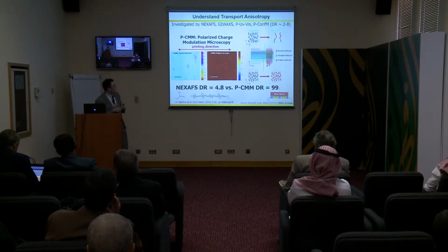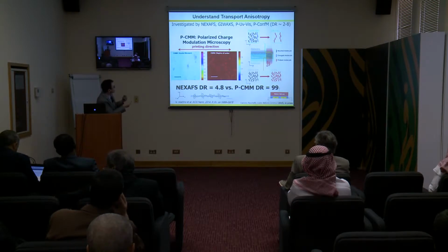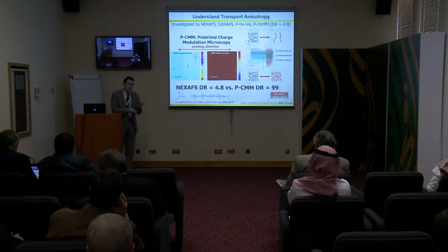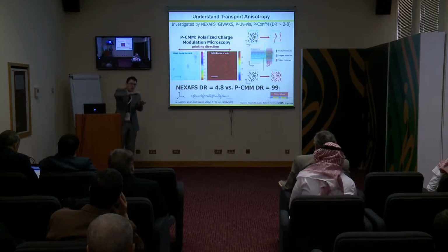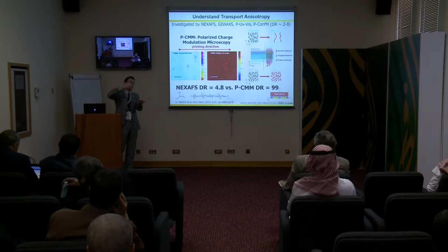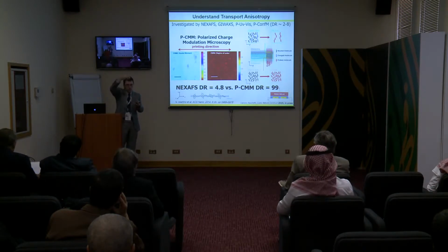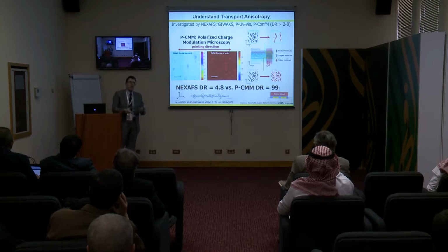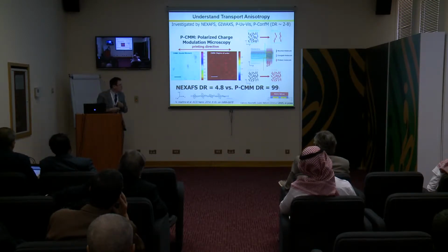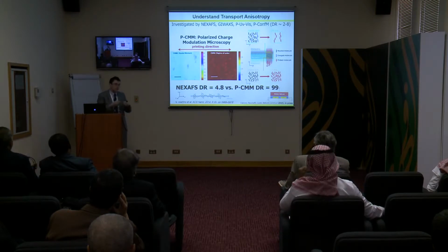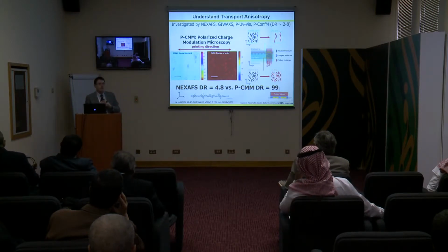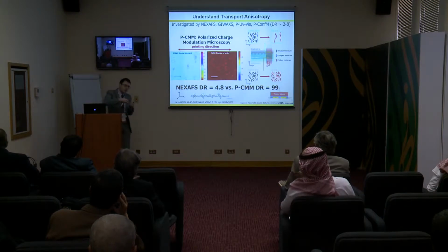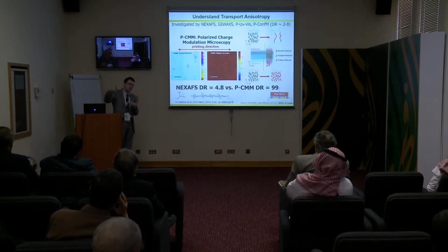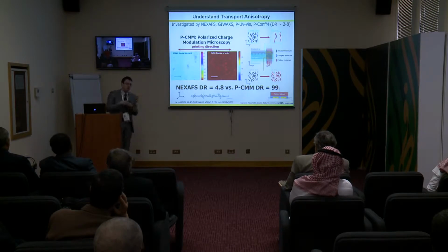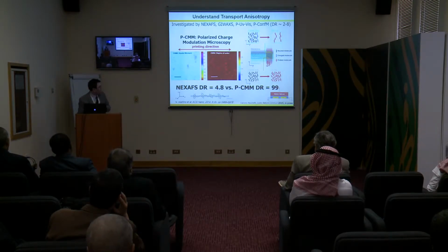And this is really because these macromolecules get oriented. And we actually spent quite some time to really understand what is the degree of alignment and where the alignment is confined, because you can think about the film thickness. Where are these macromolecules aligned? Is it at the surface? Is it the bulk? Is it the bottom interface? So using a variety of techniques, we could understand that the alignment is preferentially at the surface, and this polymer which is aligned is where the charges get confined and get transported. This is what this work has told us.